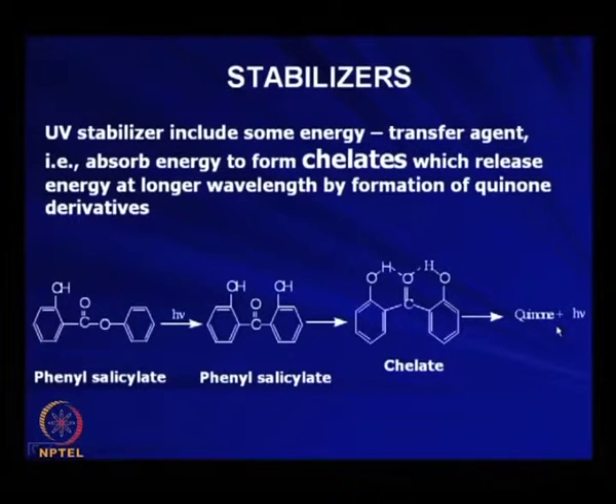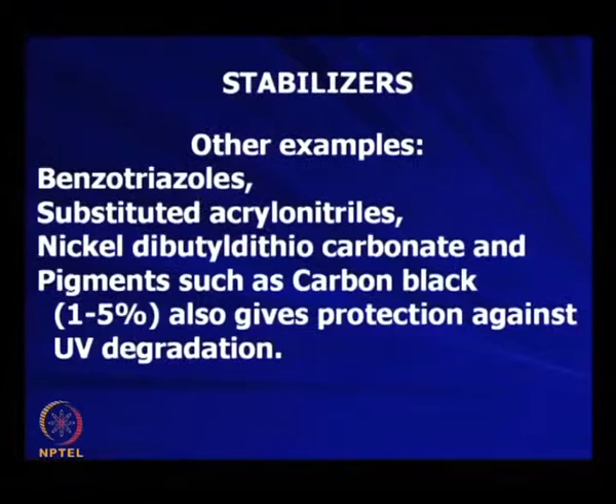One more thing, carbon black. You see almost all overhead tanks are black, isn't it? 1 or 2% of carbon black is blended with this plastic, HDPE, because carbon black absorbs this UV without any harmful effect on the polymer. So, UV is absorbed by the carbon black before it reaches the carbon-carbon and carbon-hydrogen bonds of the polymer. So, it stabilizes the polyethylene. So, the use of carbon black in this tank is not as filler, but as UV stabilizer. Other examples: benzotriazole, substituted acrylonitriles, nickel dibutyl thiocarbamate, pigments. Carbon black at 1 to 5% also gives protection against UV radiation.